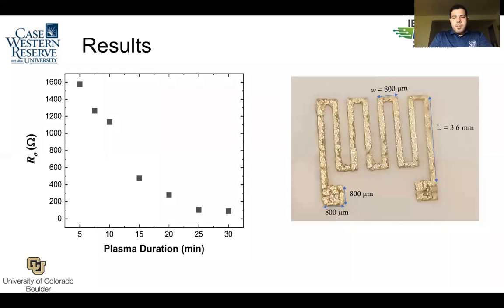So here are the results. The picture on the right-hand side shows you a sample of the strain gauge. And here on the left-hand side, you have a plot of resistance versus plasma duration from 5 minutes to 30 minutes. At 5 minutes, the resistance was 1600 ohms. At 30 minutes it was nearly 100 ohms. And you see that the resistance decreased exponentially from 1600 to 100 ohms. So after we plotted this, we know the longer the plasma exposure, the greater the conductivity.